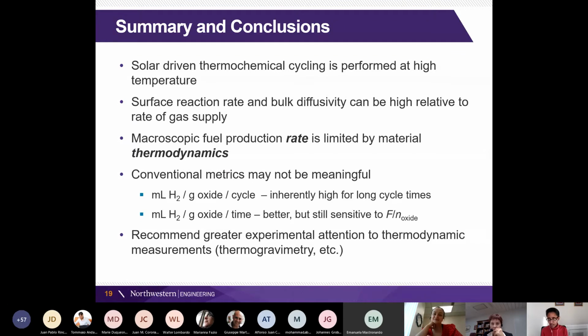So you think about some unusual forms of entropy. For ceria, the argument has been that there's some electronic entropy contribution that gives it a high entropy. Are there magnetic sources, things that don't necessarily give you a structure change? Because from my perspective, that causes the material to fall apart, makes it hard to cycle. I don't know of any other examples of 500 cycles of a given material. So magnetic entropy may be the way to find something, but I don't have an example.